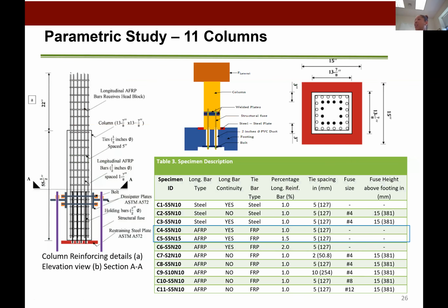So in putting all this together, we have this numerical model with this square column as shown, the column reinforcing details with the energy dissipators, 4 of them attached to these steel plates, where again, we're trying to focus the damage in this region. So the idea is that we're just replacing the fuses. So again, a lot of information of things that we looked at, but let's focus our attention for these results mainly on model specimen C4 and C5, where we varied the longitudinal reinforcement ratio at 1 and 1.5%, and a tie spacing of about 5 inches.